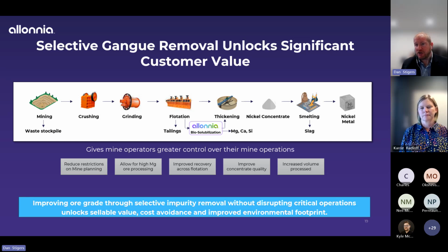Once it goes to the concentrated smelter, you should be able to push further production of your nickel through the circuit at the end of the day, because what's known with magnesium is that as the concentration builds, the temperature required in order to smelt goes up and the throughput goes down because of the viscoelastic problems with the slag. So by cutting that magnesium level lower, you should be able to smelt your nickel at a lower temperature, saving on energy, saving on CO2 emissions.